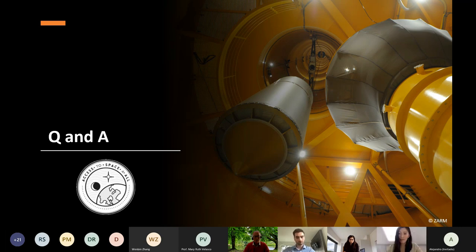I think maybe it depends on the welding process, because there are a lot of forces in welding, like Lorentz forces if you're arc welding, Marangoni surface tension forces. So the gravity force would be removed, but I think in a lot of welding processes, the force of gravity is overwhelmed by other forces, leading to liquid flow. So my guess is that the weld itself may not be all that different,